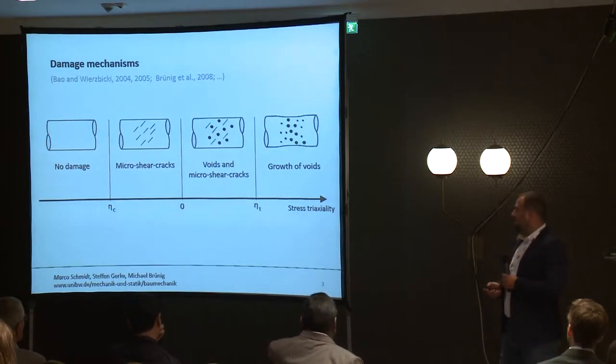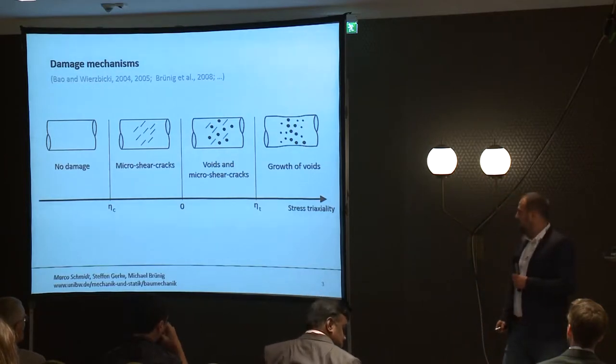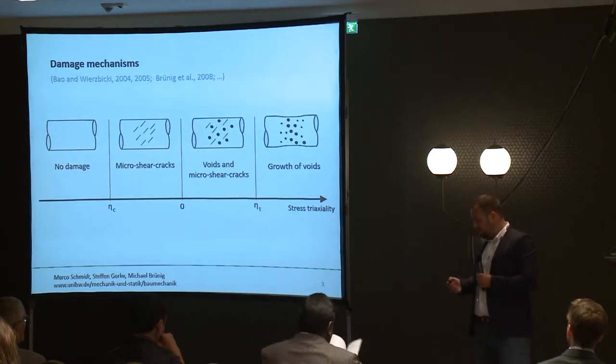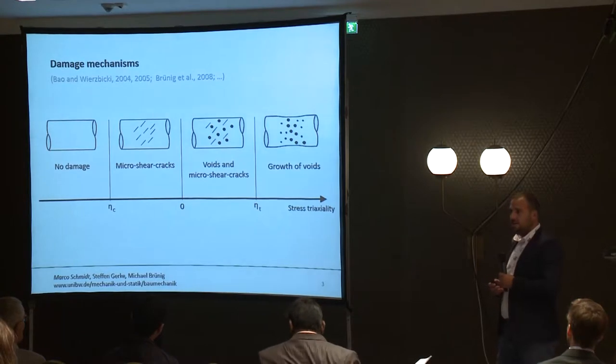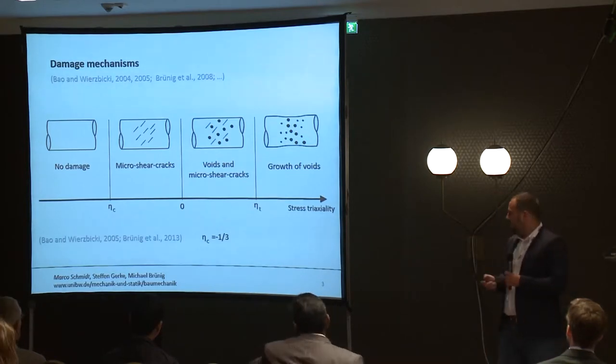Furthermore, the idea is that there is a limit for negative stress triaxialities, also called cut-off value, below which no damage occurs and ductile materials don't fail. To investigate this limit is one part of our research. So far, the cut-off value has been assumed to be minus one-third.